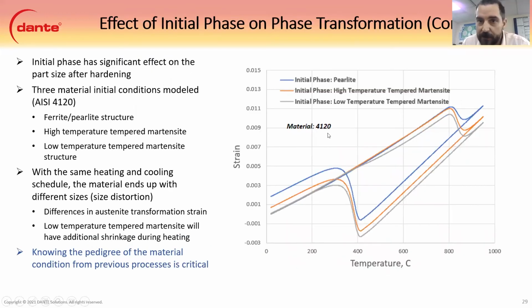So here's more about the initial phase. We could start with, say, an initial phase of pearlite. And they all start on this gray line here. The overlap is kind of misleading a little bit, but they all start on this gray line here. And the blue line, you can see there isn't very much variation. It's pretty much a straight line. Comes up to AC1, starts creating austenite, finishes austenite, and then we start cooling down, and we get martensite. And then the second one is the orange one here, and that was a high temperature martensite. So it's already pretty much tempered almost completely.